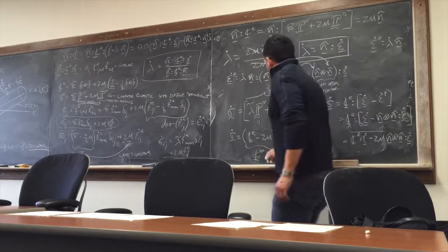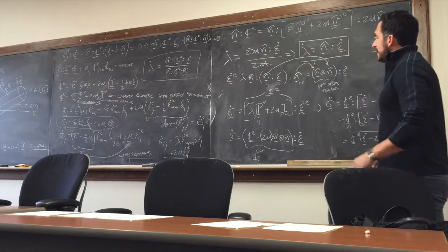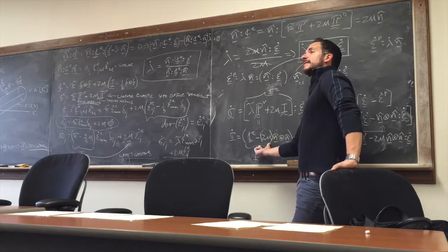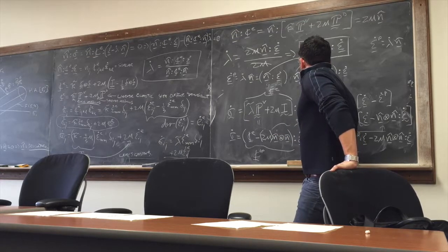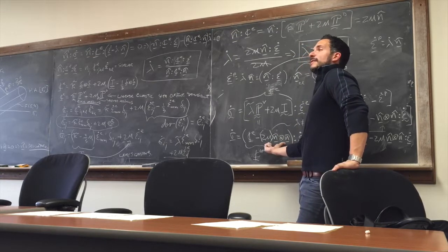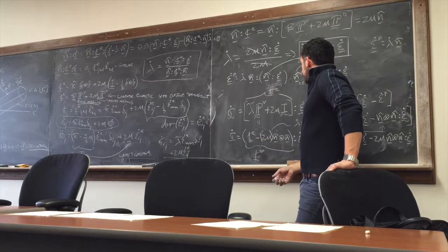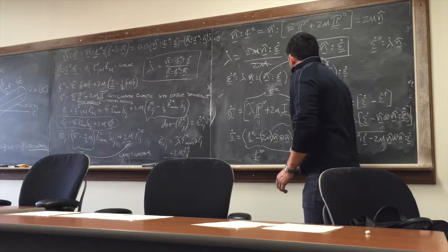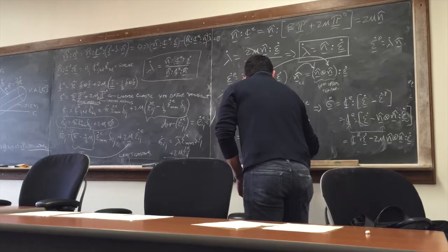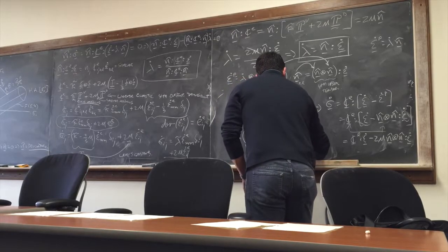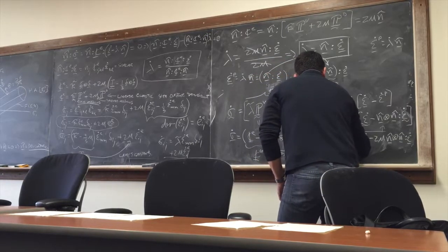Okay? Many people like to write this thing in Macaulay brackets, meaning that this only gets activated if you have plasticity. So, in other words, if lambda dot is not equal to 0, then you activate this corrector. Otherwise, you just leave this. Okay, but that's a formality. So this is the elastoplastic tangent operator.